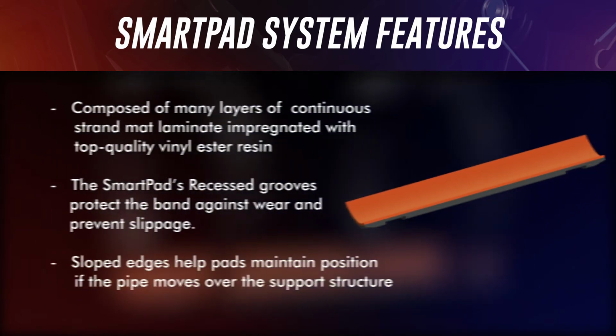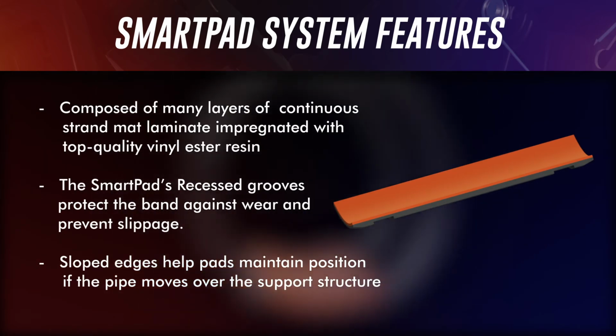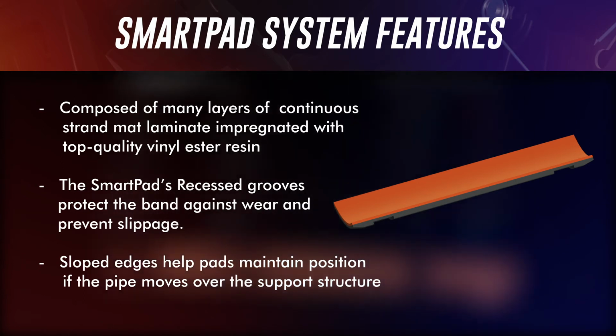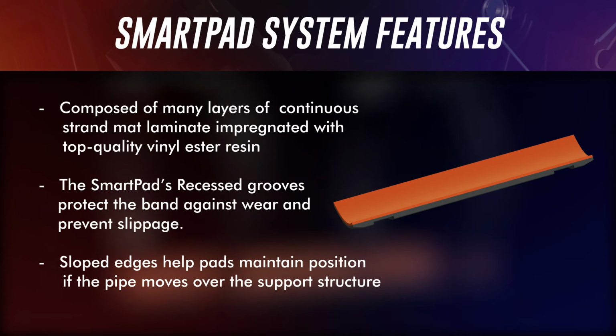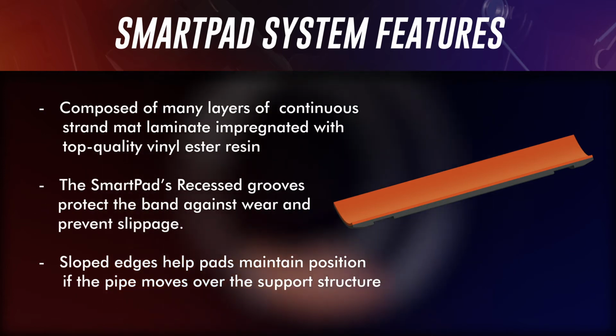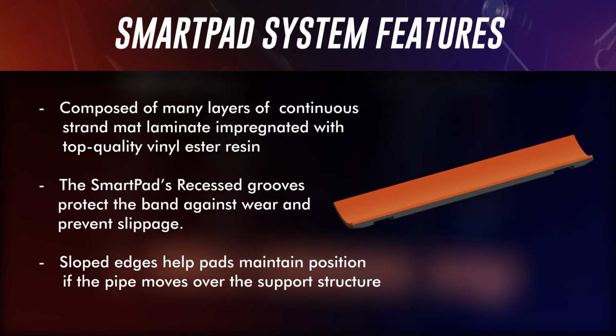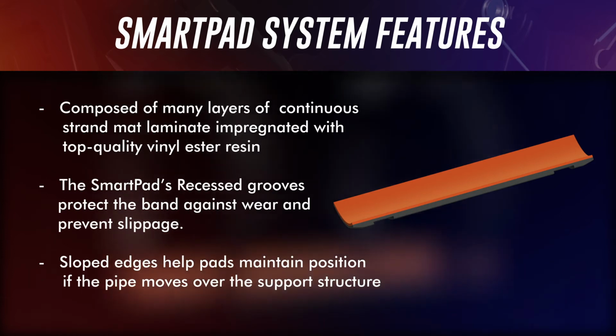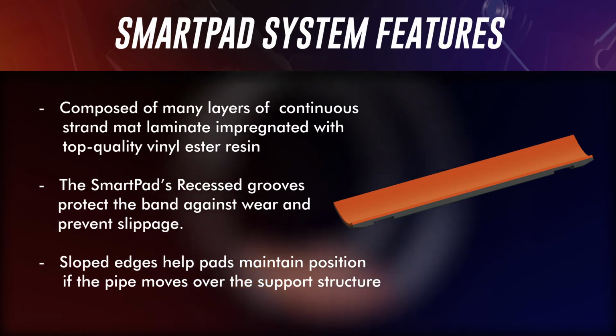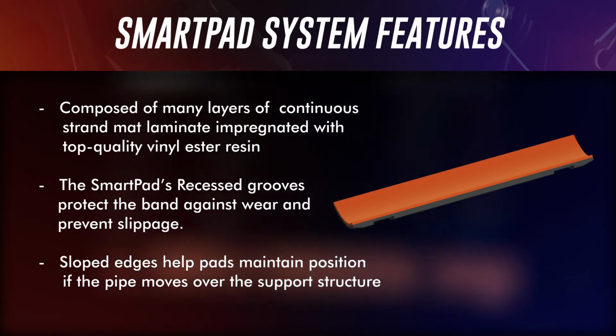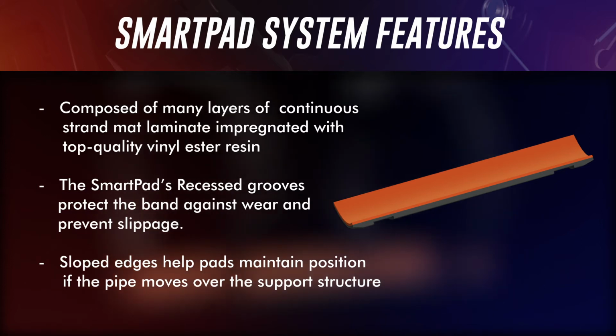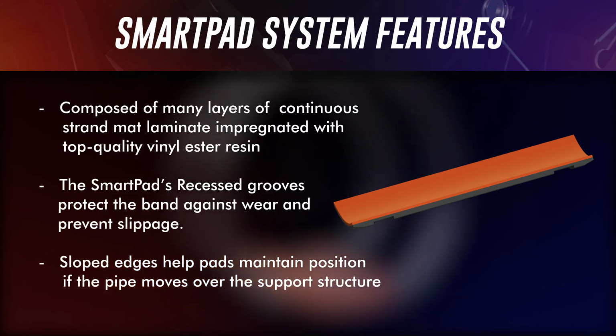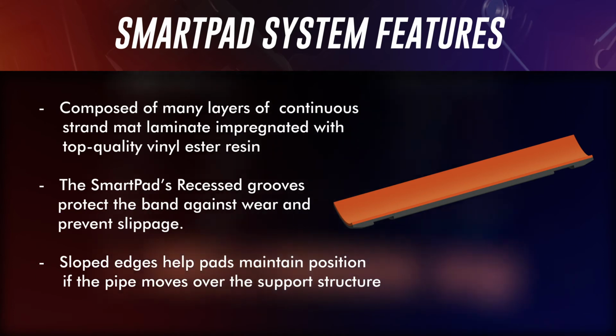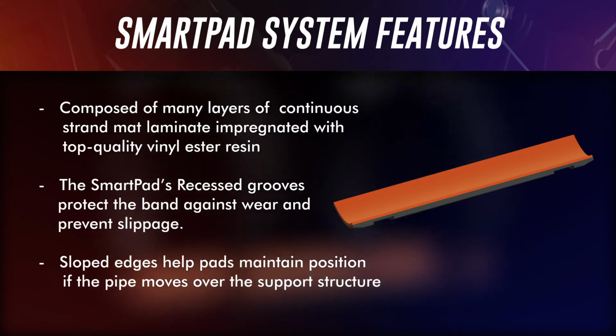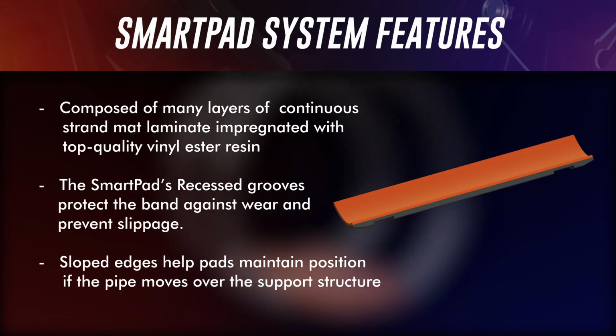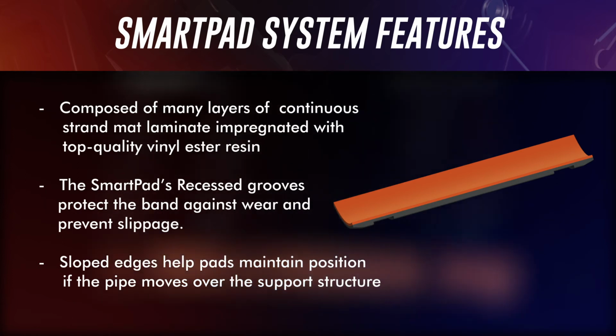They have been, however, modified or are used in innovative ways. The SmartPads themselves are made from a composite material consisting of many layers of continuous strand mat, laminated and impregnated with top quality vinyl ester resin. They are designed, manufactured, and tested specifically to be used as pipe supports, making them durable and resistant to abrasion in harsh environments, including temperature ranges between -60 degrees Fahrenheit to 400 degrees Fahrenheit, high humidity, below the waterline, and even in chemically corrosive applications. The grooves inset into each SmartPad guarantee that the pad remains securely held to the pipe by the smart bands.